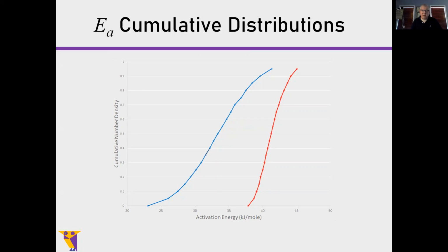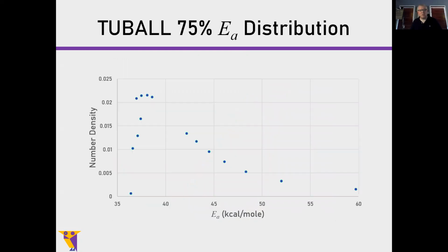Now, to me, that at least suggests that, in terms of chemical heterogeneity, blue is probably far more heterogeneous than red. I don't have any proof of it, but at least I have something that suggests it, and I have a test that I can run, and I can quantify it, and I can analyze it. And even better than that, I can have this analyzed by my peers. I have asked some people, and I'll credit them at the end of the talk, with having checked this over. I mentioned at the beginning the Russian company TUBALL, this is their product. When you actually plot the distribution as a standard distribution, you get something called a Weibull distribution. I'm not sure why.